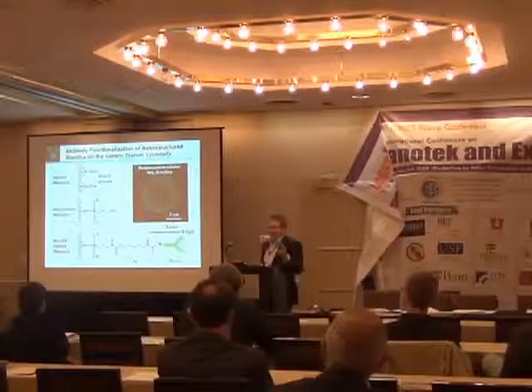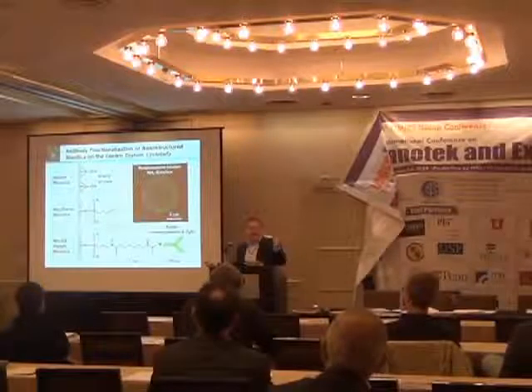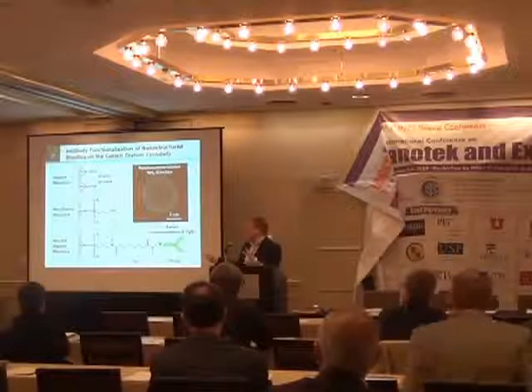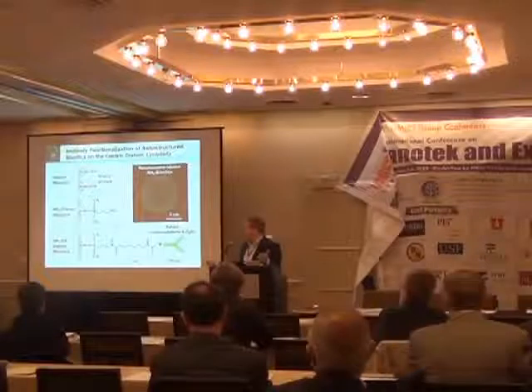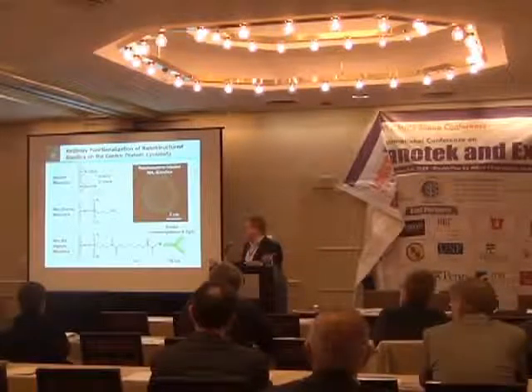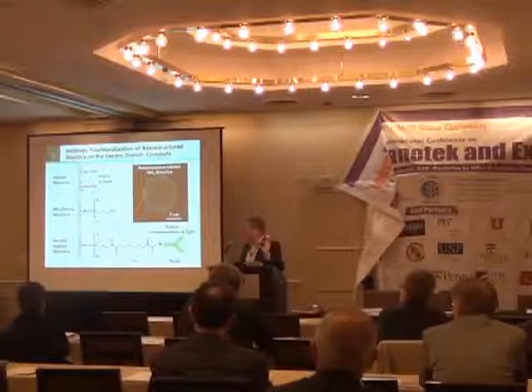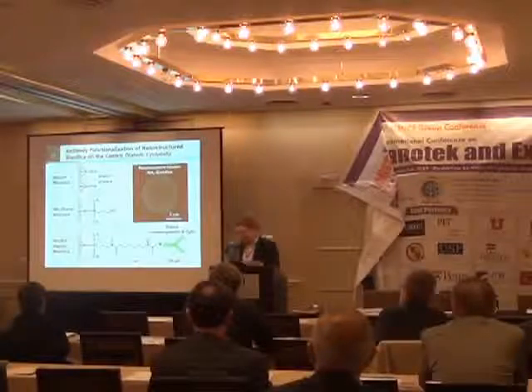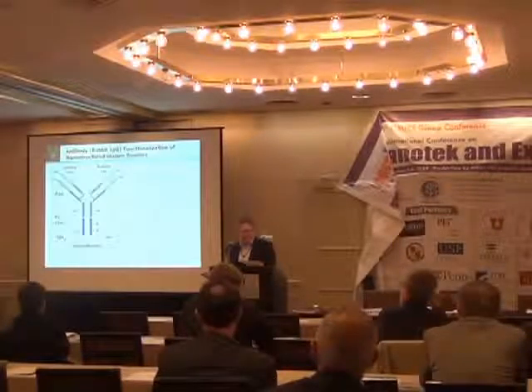Before showing that, I'll overview how we get the antibody onto the surface. Unlike glass, biogenic silica has many silanol groups because it's an amorphous material, so it's readily functionalized with an amino-functionalized surface via aminopropylsilane. With those reactive amine centers, we use a common biomolecule protein cross-linking agent — in this case BS3 — which provides about a one nanometer linker, allowing direct antibody coupling. We used a rabbit immunoglobulin G antibody as a model system, and results indicate pretty uniform coverage of the amine groups to prepare the system for functionalization.